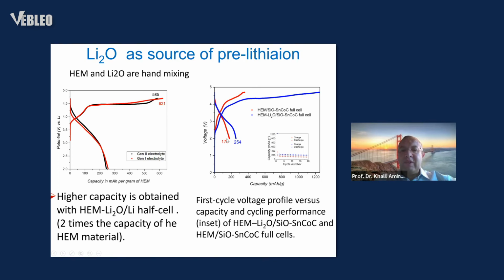We get only 176 because a lot of lithium is lost because of the cathode. Lithium from the cathode has to compensate for the irreversible loss of the silicon. However, once we add the lithium, you can see we can recover the whole capacity. So this is an approach.